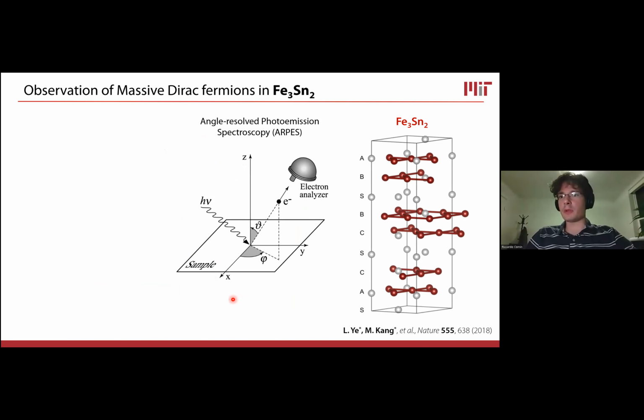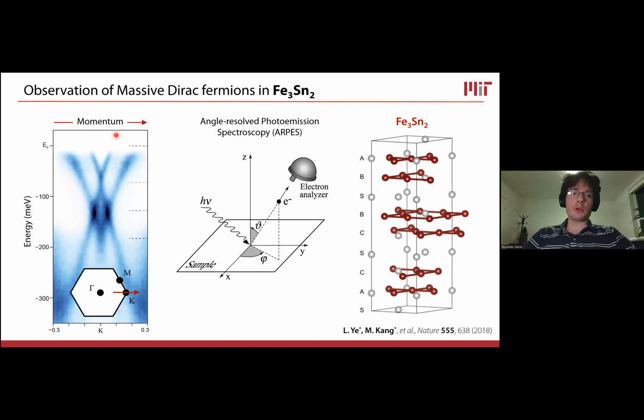I know many of you are familiar with the technique. It's a fancy version of the photoelectric effect that was discussed by Einstein. Essentially, we shine ultraviolet photons onto our sample. We can photo-eject electrons right from the surface because of the short mean free path of electrons in matter. And then we can analyze the energy and the takeoff angle of those electrons. And from those, simply by applying conservation laws, we can reconstruct the energy and momentum dispersion of the electronic bands inside the solid. And so you can generate these beautiful maps.